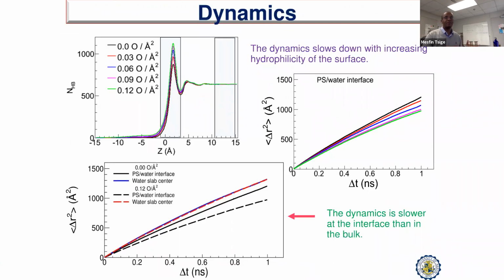With that interfacial approach, we are also characterizing the dynamics. If density is increasing with degree of oxidation, we should obviously expect that the dynamics should be decreasing. And that's what we have actually observed here. On this one, I'm showing the number of hydrogen bonds as a function of distance. This is the number of hydrogen bonds formed by water molecules with the substrate and among themselves. Of course, we see an increase and finally more like saturation. And above 6 angstrom, we recover back to the bulk value.